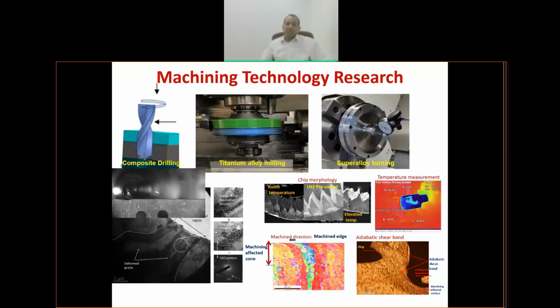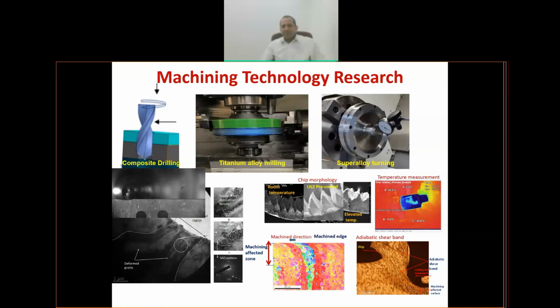Machining is not done just for metals. However, of course, we also do composite machining. And composites is a field by itself. So this is one area which my group is involved in. A lot of fundamental understanding, just to give you some colored images of what they're about. So for instance, the colored image which you see at the bottom is the electron backscatter diffraction micrograph. So this is an electron backscatter diffraction micrograph of the subsurface microstructure.